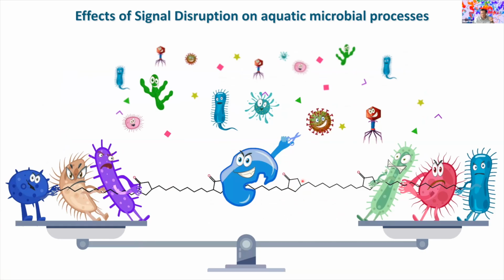Now, when we introduce the enzyme and the enzyme starts to chop those signaling molecules, well, that balance is disrupted. And that equilibrium changes, and this change in equilibrium changes the course of events. And the biological processes that are normally very robust and will occur very reproducibly are now on a different course, and we see some changes there. That also means that for us, there is the potential to modify these enzymes so that we potentially target specifically the few bacteria that are most important to the process we're interested in. For example, in regards to zebra mussel, if we know what bacteria are most important to zebra mussels, then we can potentially make enzymes that will specifically target those and minimize the effect on other microbes.